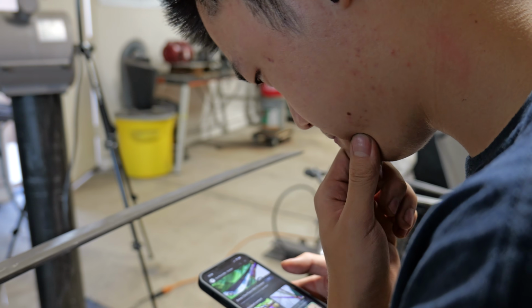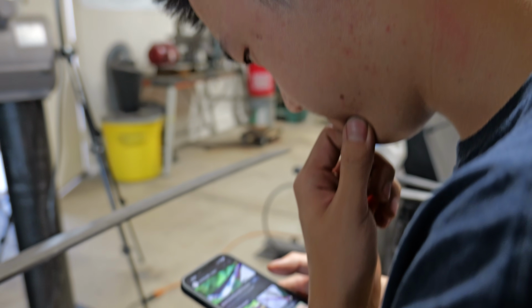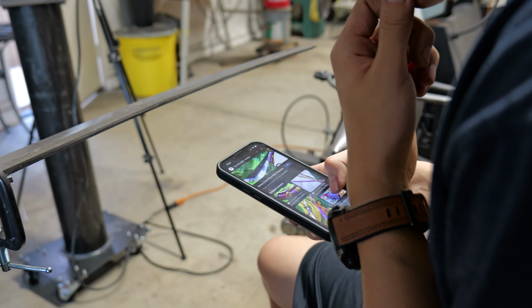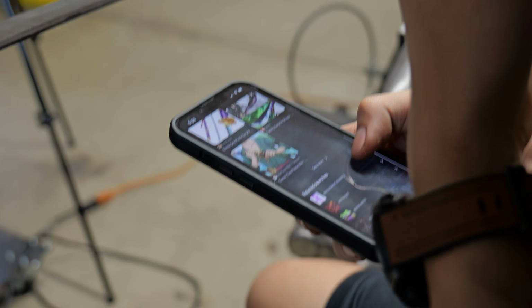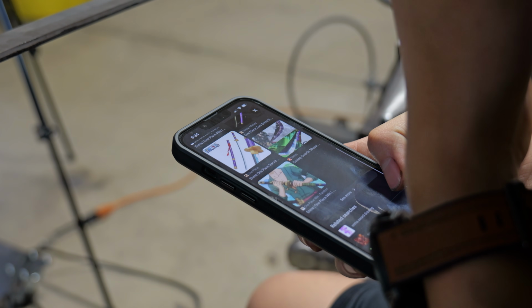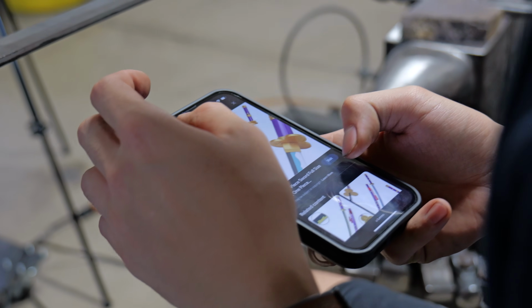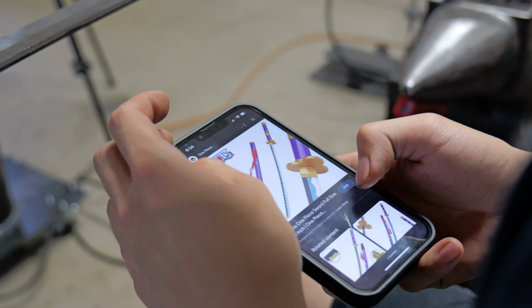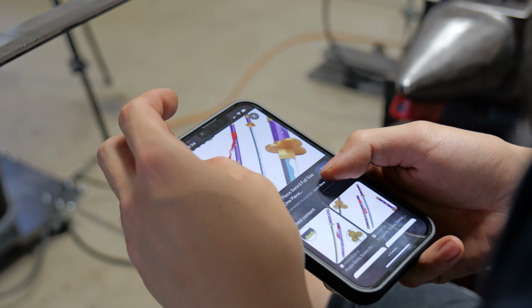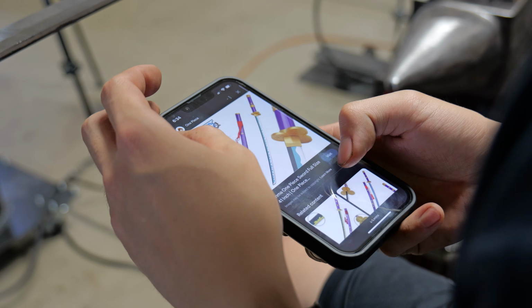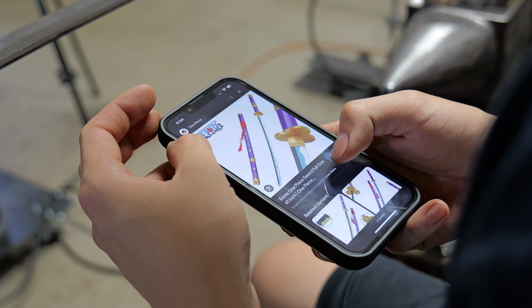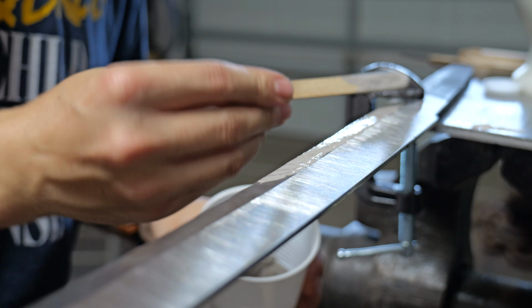At this point, I already decided to requench the blade. But what was I going to do different? I had a theory that the ashi lines were too thick and the entire blade cooled a little bit too slowly, and that made it so only the edge was hard. I decided to take another look at the hamon on Enma and do much wider swaths of clay. Maybe this would help the edge quench a little faster.